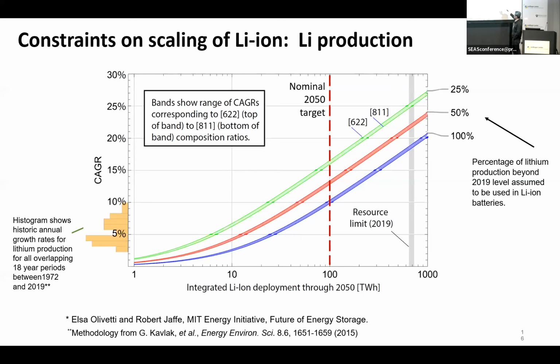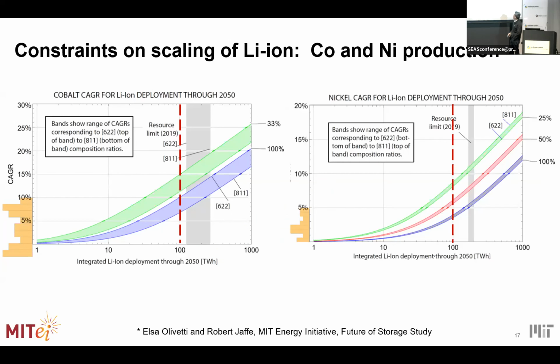So this is a complicated plot, and I'm pausing here because I'm going to show you two more just like it. Cobalt and nickel, same idea. Histogram on the lower left: what's the CAGR of production, historically, for each of these metals? What does it have to be to reach that 100 terawatt hours? And again, you come to the same conclusion for cobalt: there's a precedent of 10% in one year, but now we have to do that over 28 years, nonstop, to get to this kind of target. And nickel is a little bit easier, but still a very significant lift.